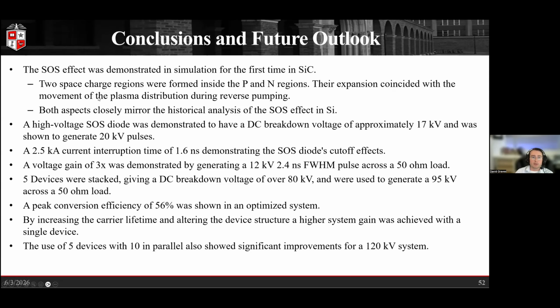Both of these aspects mirror the historical analysis of the SOS effect in silicon carbide, or in silicon, I should say. With that, we did demonstrate a high voltage SOS diode, which had a DC breakdown voltage of 17 kV, and we could generate 20 kV pulses with that.